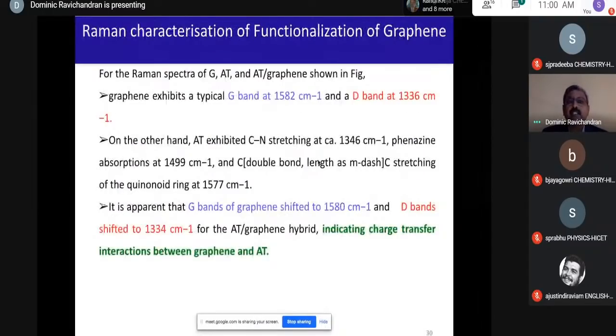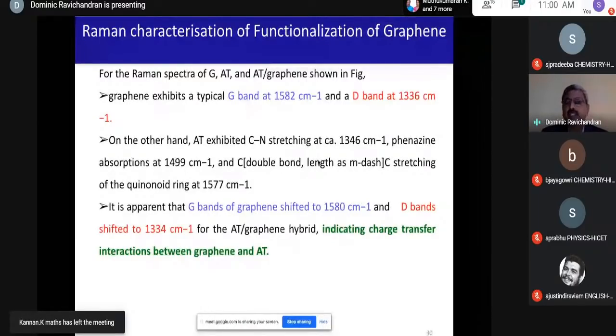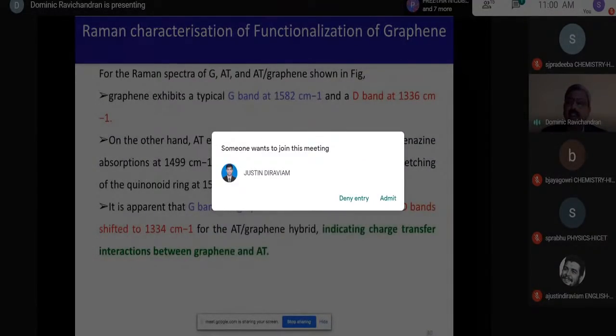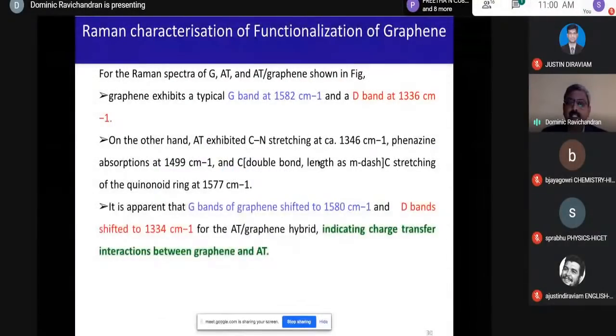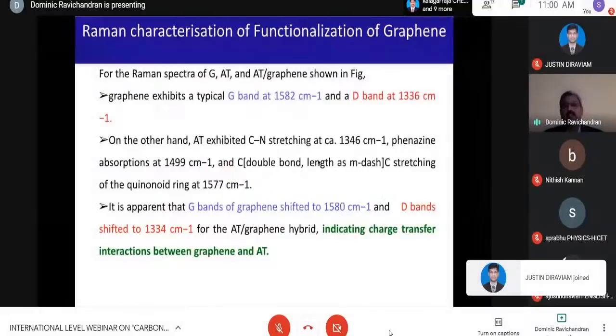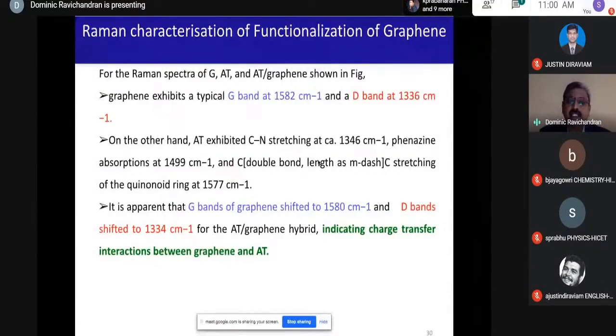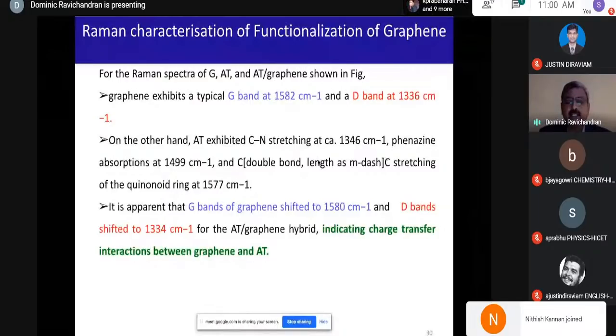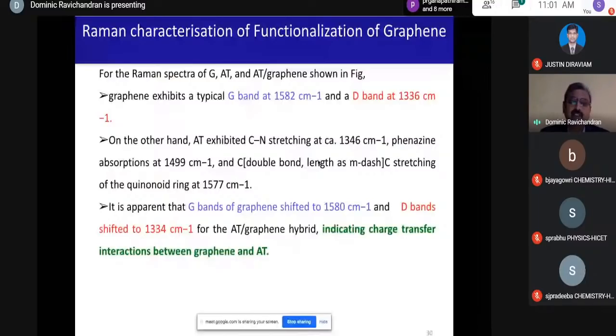In case of the Raman spectroscopy, for the Raman spectra of graphene and aniline trimer, graphene exhibits a typical G band at 1582 cm⁻¹, which is a special peak for graphene, and a D band at 1336. In case of pure graphene, it will not have the D band. In most cases, because of some disturbance in the graphene structure, you'll have a D band at 1336 cm⁻¹. The ratio between this G and D band will indicate the type of distributions and disturbance that you have in the graphene sheets.